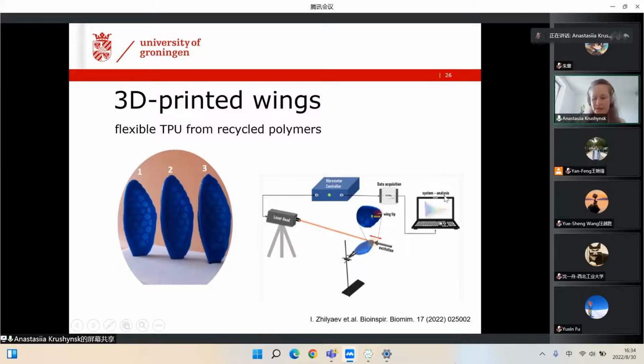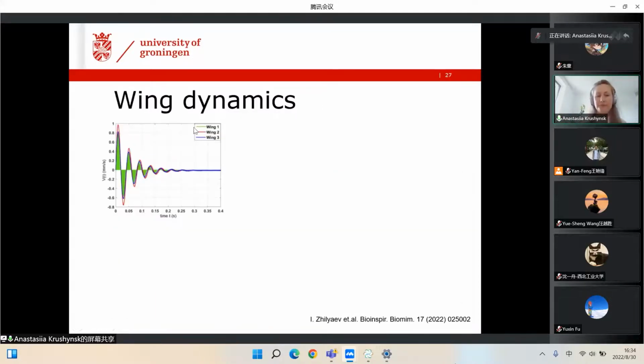So for the 3 samples that you see here, we measured many times the free vibration response. So here is an example of one set of measurements. And as you can see, the amplitude is different because we use manual excitation. So this is experimental data. We used them as initial input for Fourier transformation.